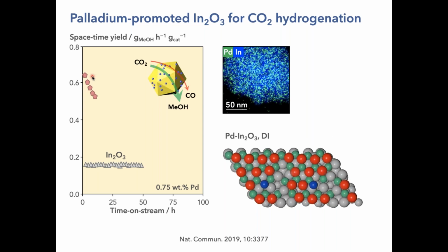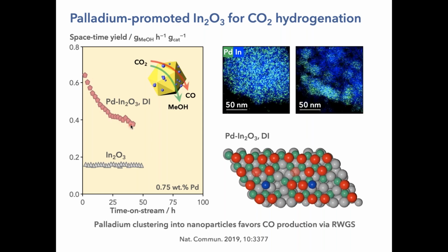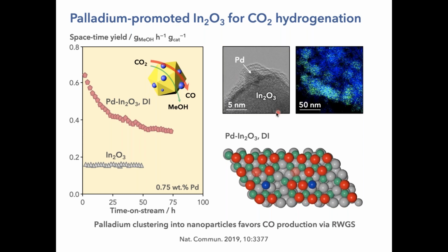But what happens is that during reaction, the activity declines heavily, because these palladium atoms are quite mobile and they cluster into nanoparticles on time on stream. So if you analyze the catalyst after 75 hours, you started with almost a single atom of palladium, very well dispersed, and you end up with a pretty large palladium nanoparticle, which catalyzes the reverse water gas shift, and that's why the methanol productivity starkly decreases.